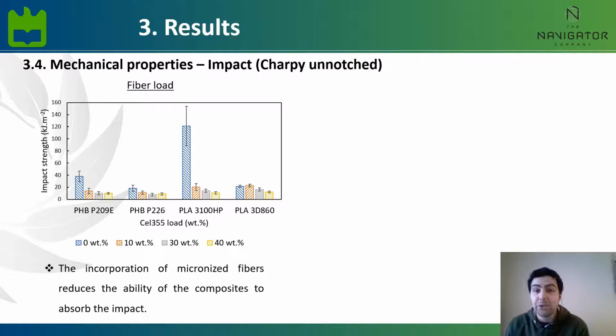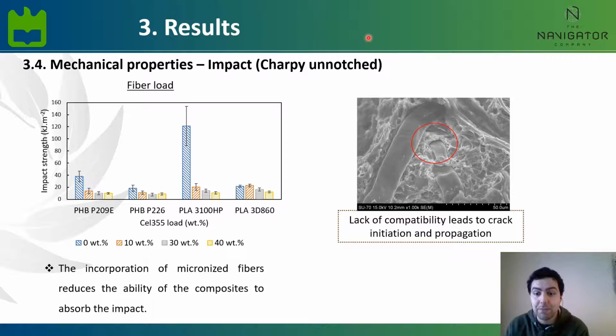The effect of the fiber incorporation on the impact strength in biocomposites is still unclear, but in our work, the increasing load of micronized fibers led to a reduction of the Charpy impact strength, as we can see in this graphic. And although various factors such as the crystallinity and stiffness of the fibers and the matrix can have an influence, the decrease in the impact strength is most likely due to the poor interfacial adhesion between the fibers and the matrix as previously shown. This lack of compatibility leads to crack initiation and propagation, which decreases the amount of force that the material can absorb during impact.